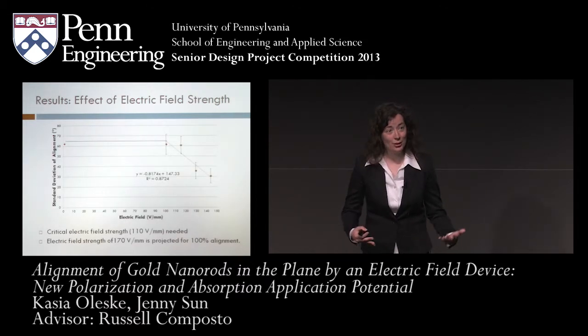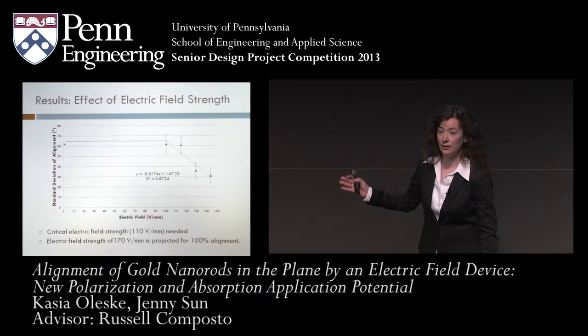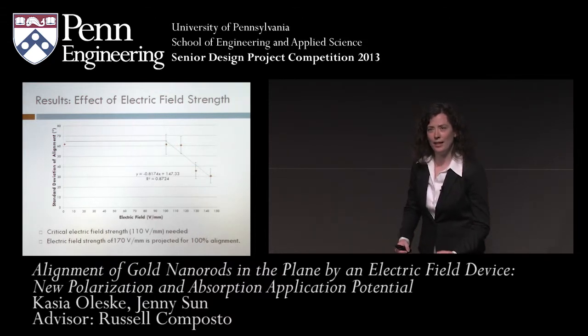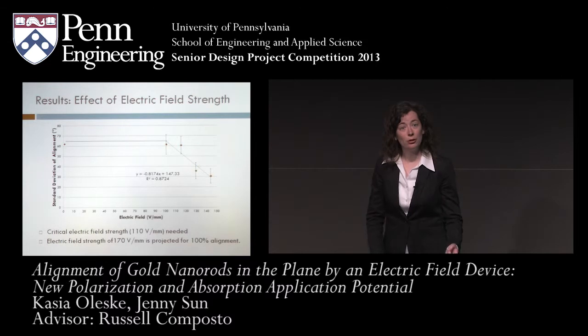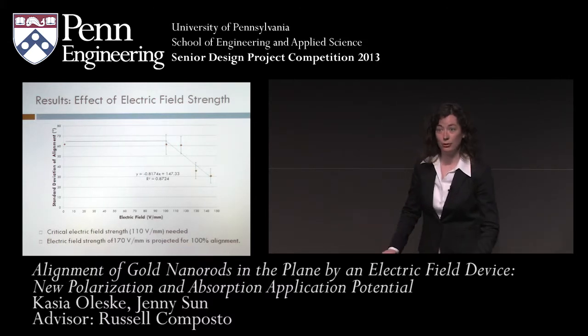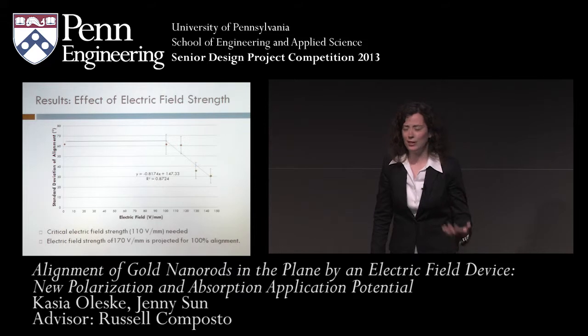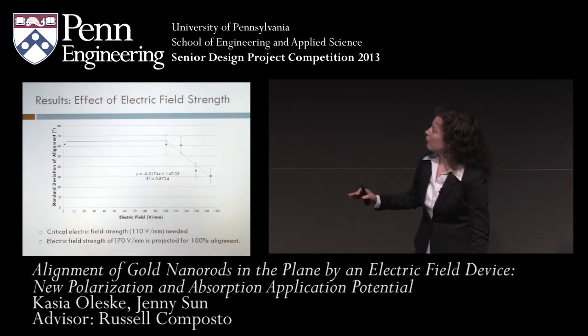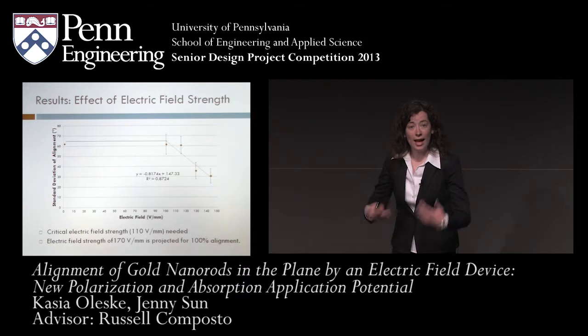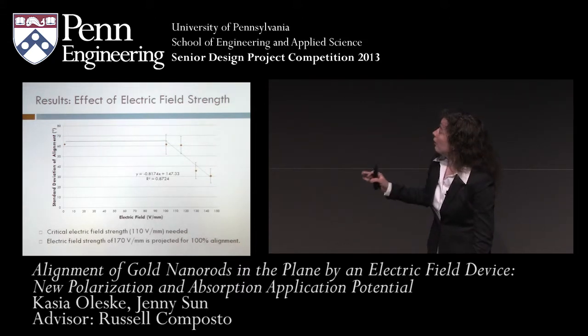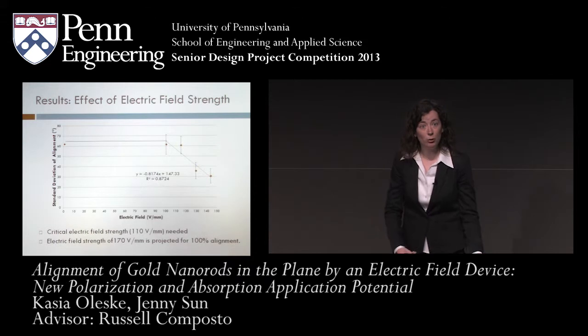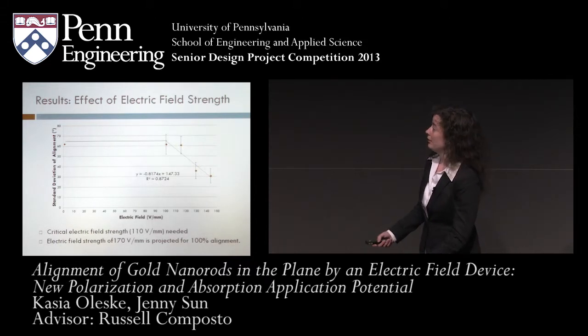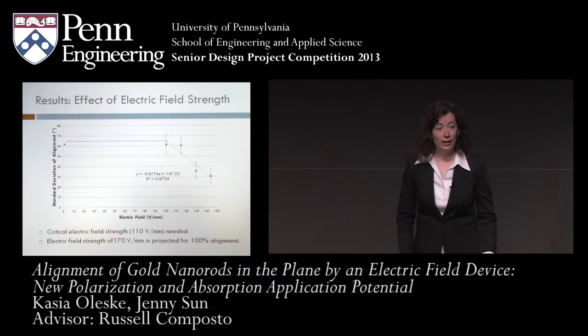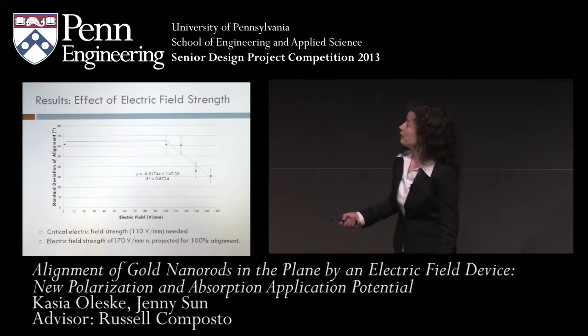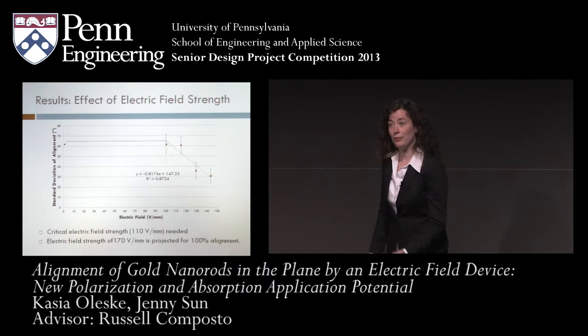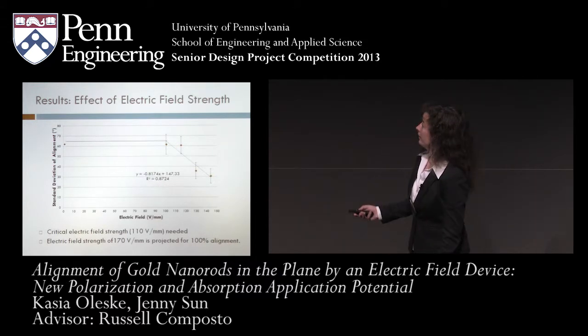So in order to attempt to do this, we plotted our experimental data, and we found two really important things. One, there appears to be a critical electric field strength in order to get any sort of alignment, which matches up with previous research. We got about 110 volts per millimeter needed in order to get any sort of alignment. Now, we want to project an electric field where we get total alignment. Therefore, we set the standard deviation equal to 0 and find out what electric field is needed. So we got an electric field of about 170 volts per millimeter in order to do so.